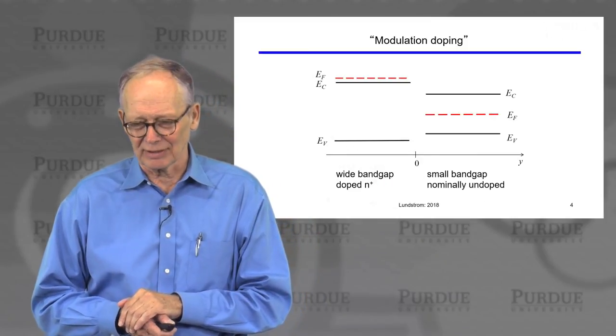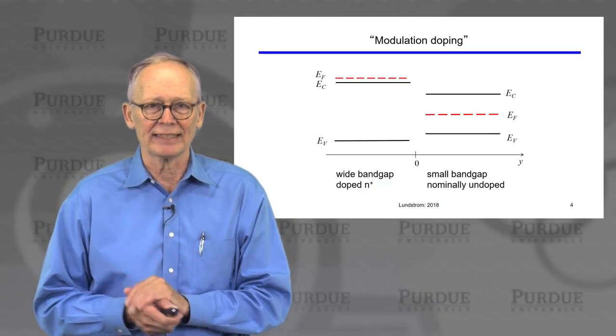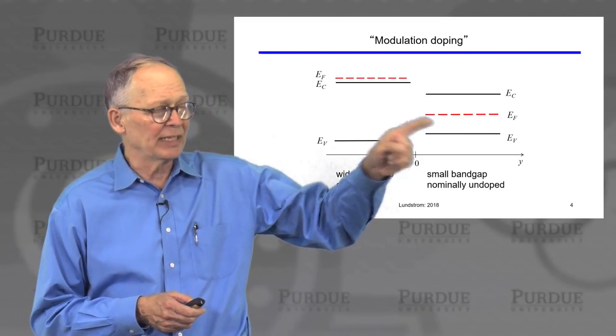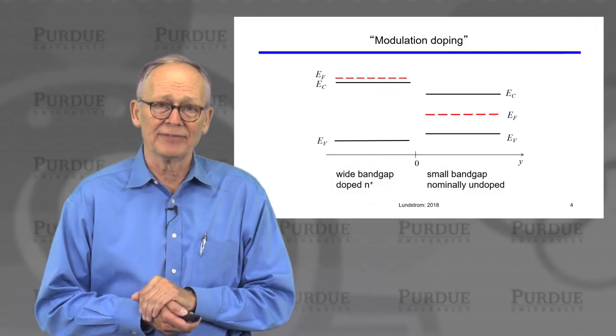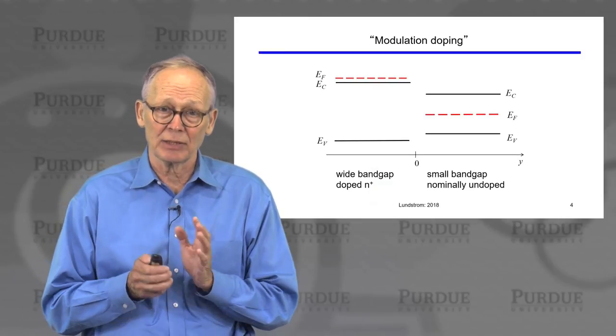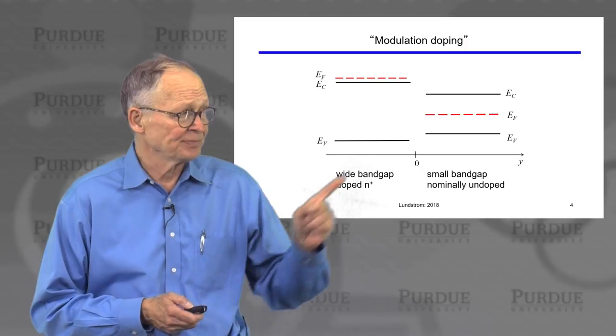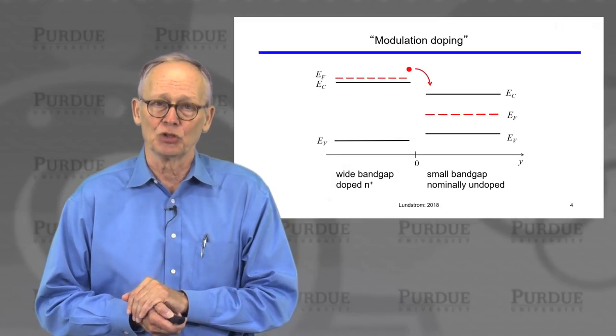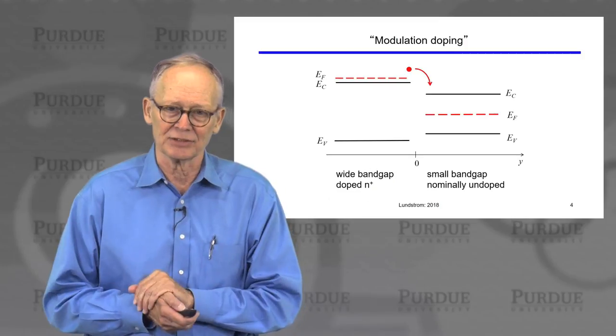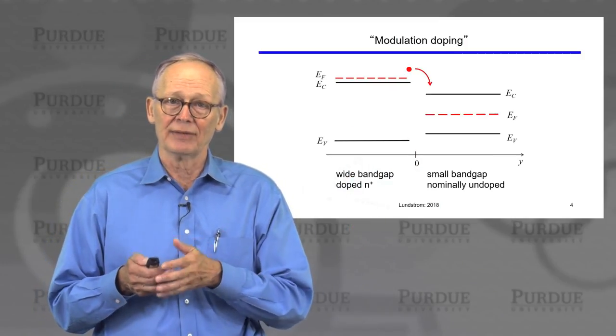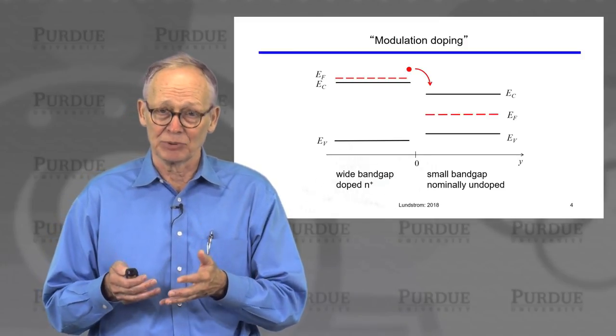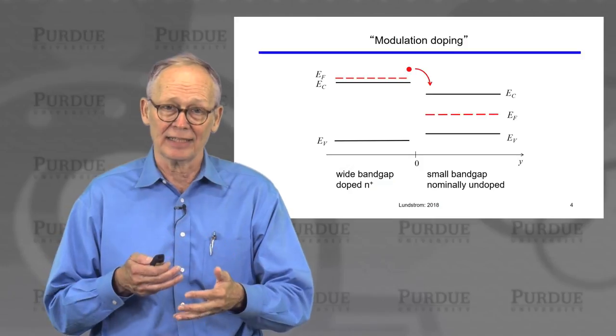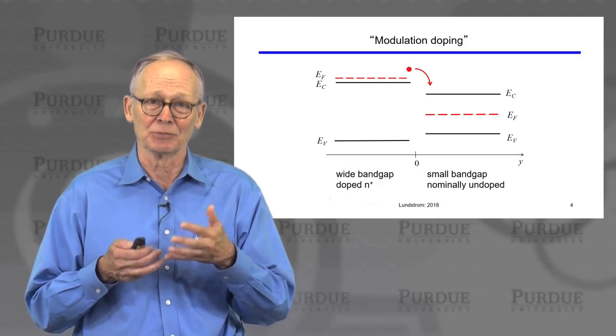Around 1980, a remarkably powerful concept was developed: a way to get carriers in a semiconductor without doping it. If we take an intrinsic small-bandgap semiconductor and a heavily doped wide-bandgap semiconductor and form a heterojunction, electrons flow from the higher Fermi level to the lower one — from the doped layer with all its ionized-dopant scattering into the undoped layer. We now have electrons in an undoped layer, giving us high concentration and high mobility. That's the 'high electron mobility' part of the HEMT.